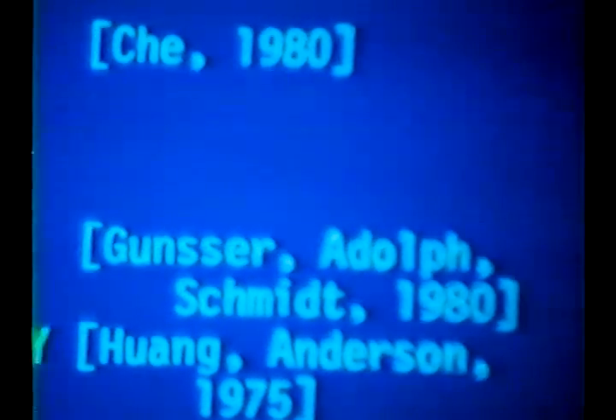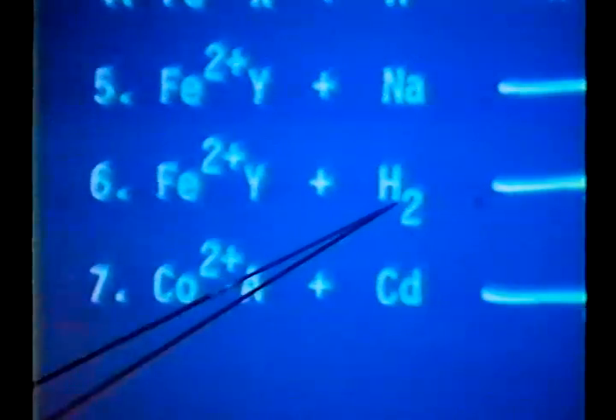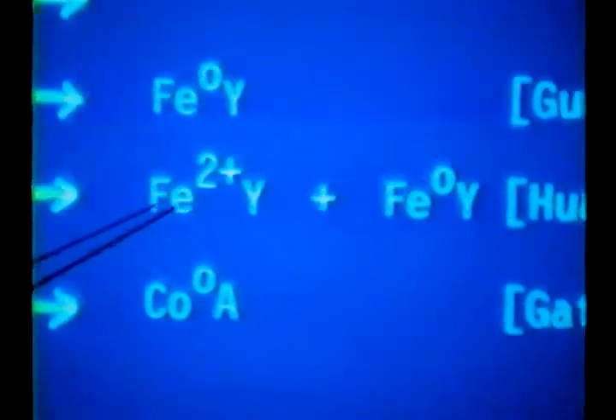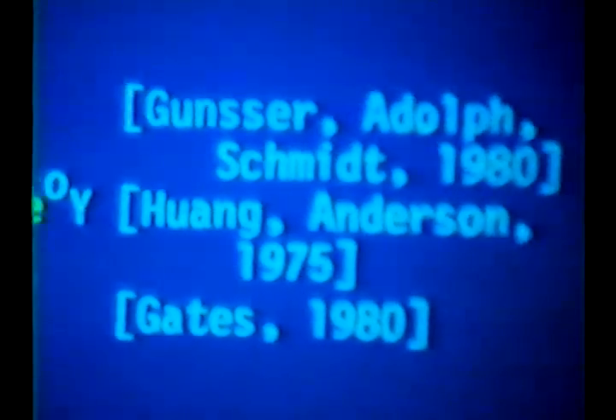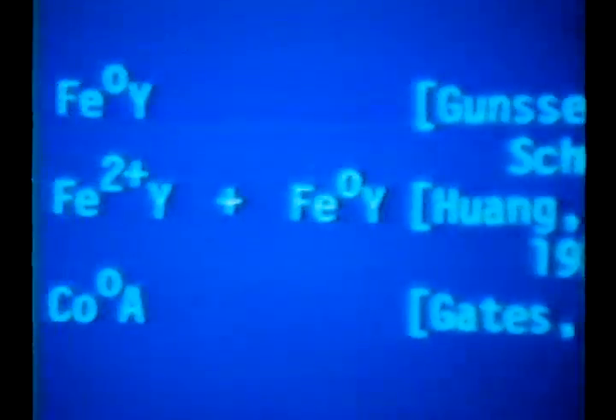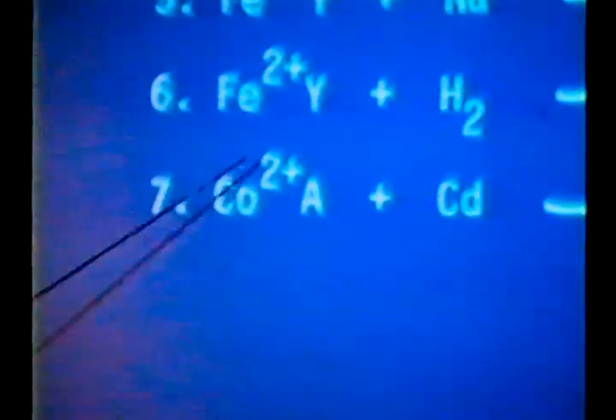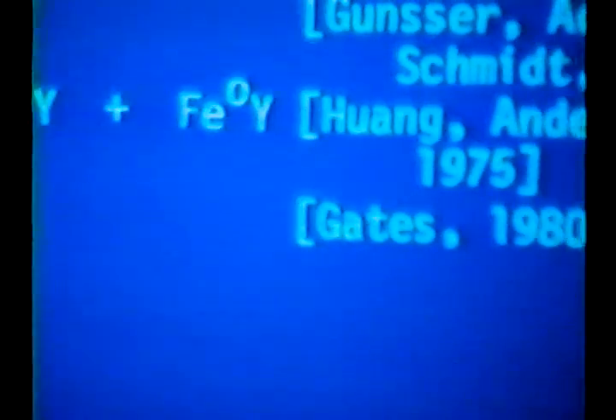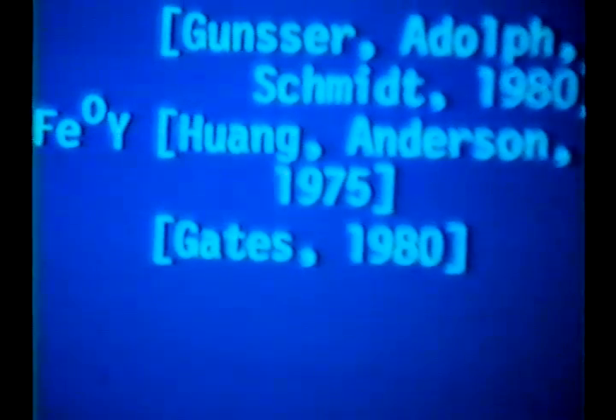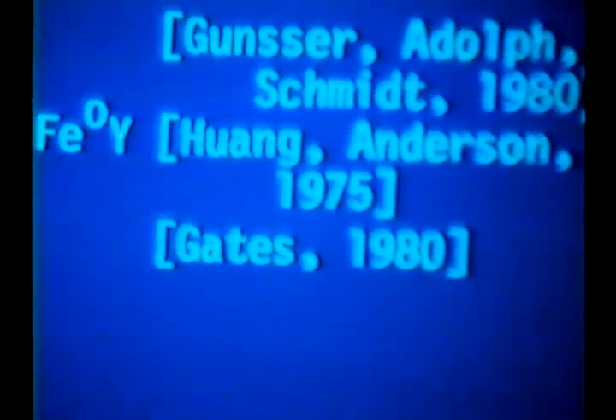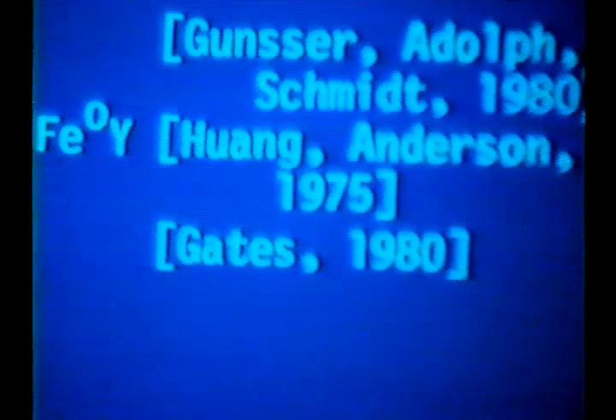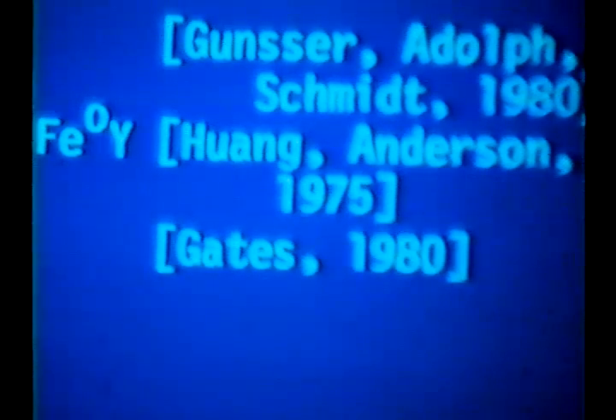The hydrogen forms acid sites in the zeolite, and the iron keeps getting oxidized. Schmidt in Germany has done some work with sodium vapor to reduce iron-2 into metallic iron. Hydrogen gas can be used. Anderson did this in 1975 to reduce iron, but what's found is not all of the iron gets reduced. Some of the iron gets reduced. And Gates at Delaware was one of the first to show that you could use other metals, cadmium vapor, to reduce cobalt ions to metallic. There are a lot of studies here. Reviews have just been published in Catalysis on metal reduction and bimetallic systems in zeolites. These are some of the types of techniques that people have used, with different types of reducing agents.